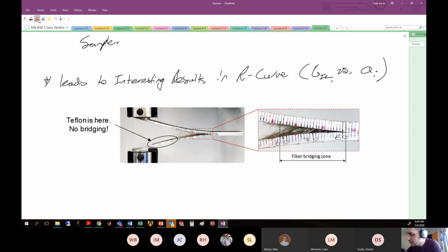All right, so here we are, another double cantilever beam. This side is being pulled open, this side is being pulled open, and you see all the fiber bridging that's occurring right at this particular location. What I'm trying to describe here is that initially here is your Teflon. No fibers. And you can very clearly see that there's no fiber bridging occurring in that region. You see this Teflon piece here. There's no fiber bridging there because you had the Teflon to interrupt it.